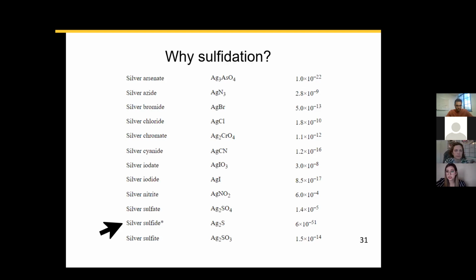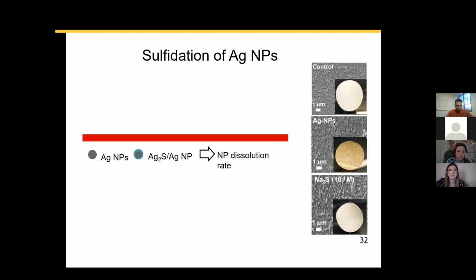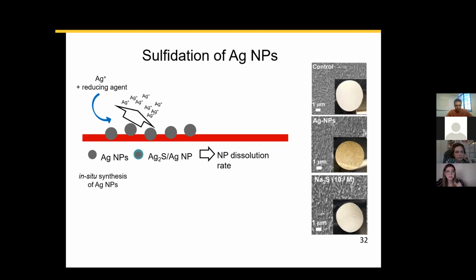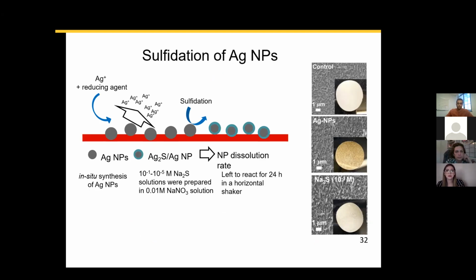So we thought this would be a good approach to try to slow down the release of silver by creating these little silver sulfide layers. What we did first is create an in situ synthesis of silver nanoparticles on a reverse osmosis membrane. We know that if we leave the nanoparticles alone, we expect a rapid dissolution of silver nanoparticles into silver ions. So we added a sulfidizing agent, sodium sulfide, to create a partial layer of silver sulfide on top of the nanoparticle surface. And that will lead to a slower release of silver ions.